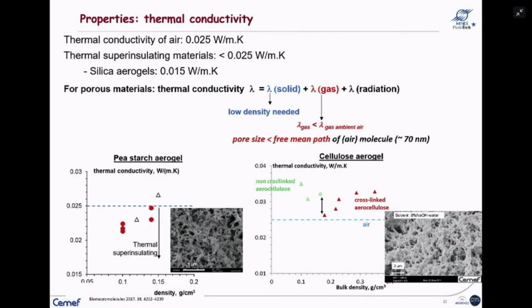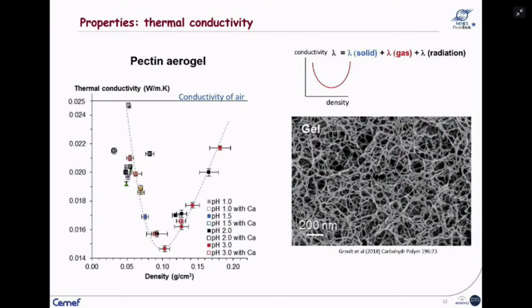But for example, for cellulose aerogel, we did a lot of work, and we didn't manage to have thermal conductivity below that of the air. Either pore walls are too thick or pore sizes are too large. Whatever you do, and to my knowledge, nobody managed. It was possible to make thermal superinsulating cellulose aerogels from nanocellulose, but not when cellulose is dissolved.